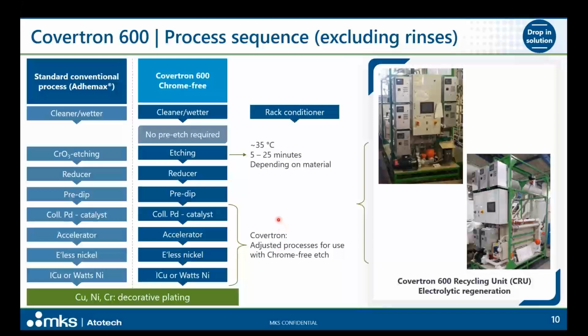When we compare with the existing benchmark process, the first thing that you can see is that the Covertron 600 works at 35 degrees. This is already an important advantage, as besides energy savings from this lower temperature of operation, it will also help when etching the parts to avoid potential dimensional changes in the racked parts, which can later contribute to stress in the plated work. This is also important: the etching time, of course, will depend on the material, but based on the experience that we have gained in our technical centers, at our customers, and with many different materials, as you will see later on, the regular etching time is from 5 to 25 minutes.